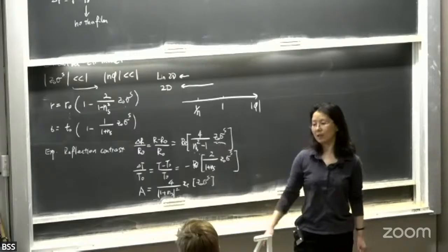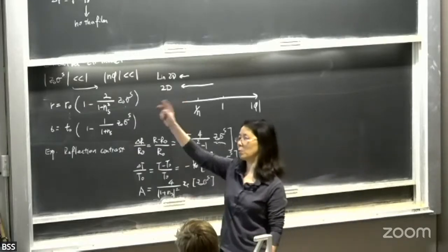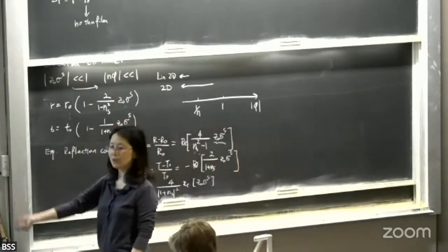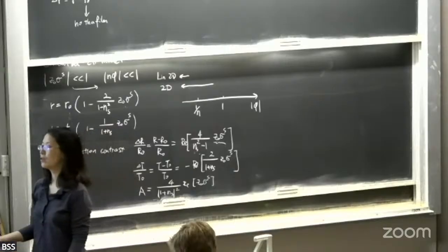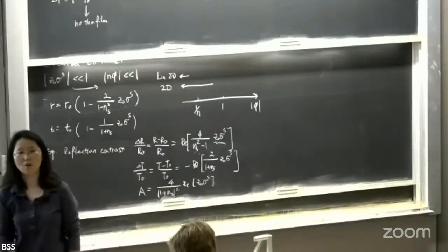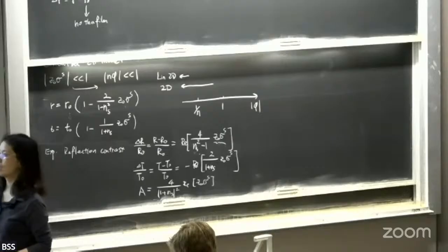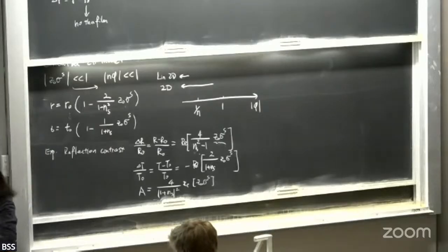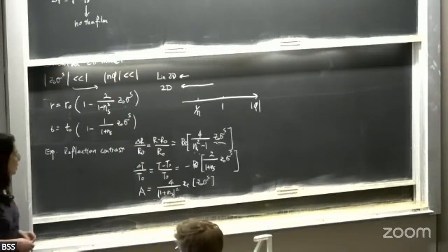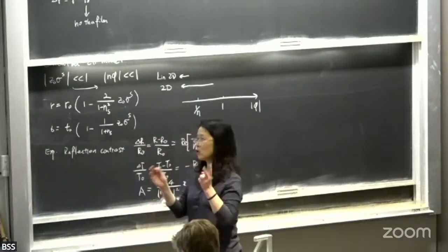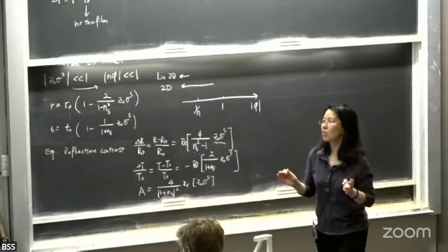Yes, exactly. So this is the first picture I showed you. People use 200 to 300 nanometer silicon oxide on silicon as substrate. So you can engineer your substrate such that you can enhance the property. Yeah, that's an excellent idea. So changing substrate is not that straightforward.